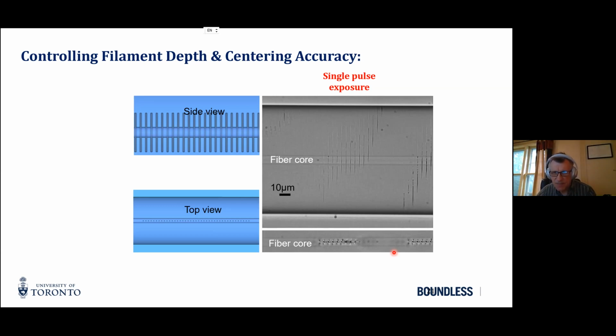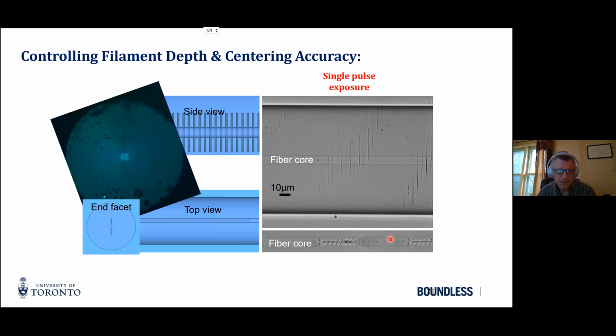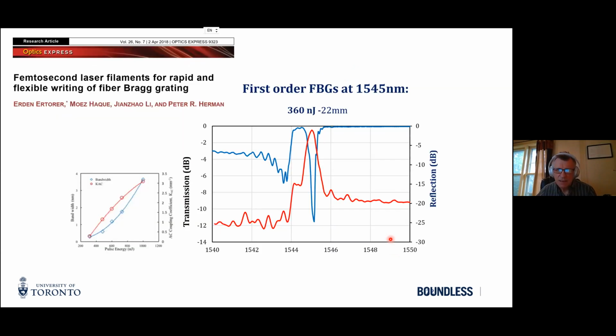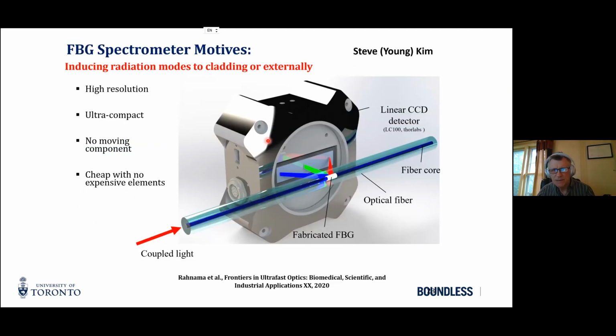So there's a top view of the filaments here, and then we can close the spacing up to almost 300 nanometers today. So with that, this is a kind of classic stop band shown here in transmission and reflection, but there's additional coupling here to cladding modes, which can be useful for sensing. And what we did here is, if we can use the filament as a kind of novel antenna shape, we can explore the idea of building a spectrometer.